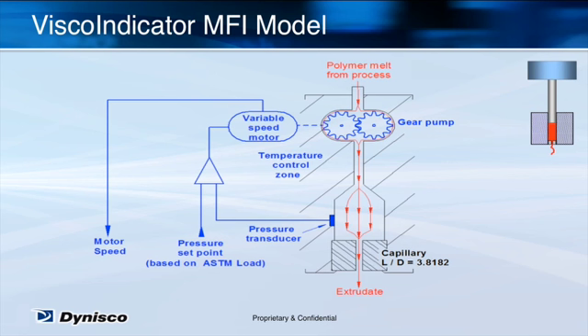In the model of the ViscoIndicator you see on this slide, a side stream is taken from the extruder as indicated by the red text in the top center. Process pressure from the extruder forces polymer melt into a metering gear pump. The pump then generates the flow rate and the pressure to extrude the polymer through a capillary. The temperature of the steel around the capillary and pump is controlled.